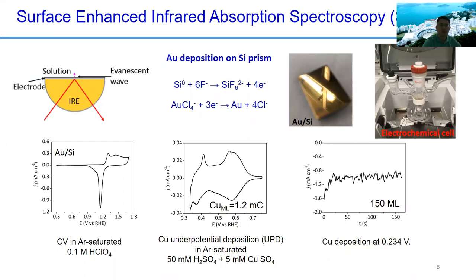So we utilize surface enhanced infrared absorption spectroscopy, or called SEIRAS. Okay. So the mechanism of SEIRAS is very similar to SERS, surface enhanced Raman spectroscopy. Also, if you want to understand the reaction mechanism, the first thing you want to know is the reaction intermediates in the process. And since this reaction is not very fast, and also the absorption of the reaction intermediates is probably very weak, we needed to amplify the signal of these reaction intermediates on the metal surface.